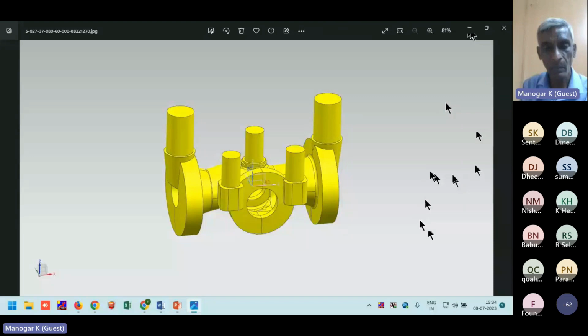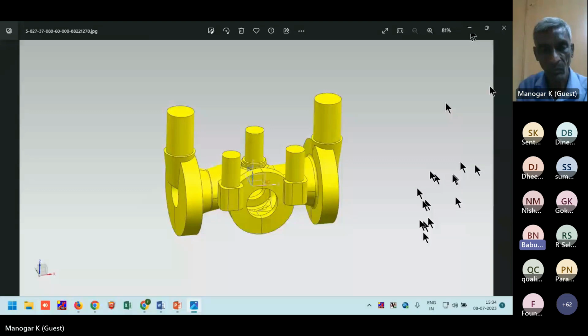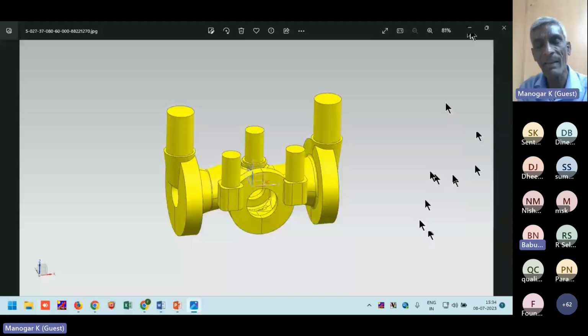Okay. So what is the general feed efficiency for the insulating and exothermic sleeve for the casting? Low alloy steel, you can take it. Less than 6 inch, you can use an exothermic sleeve so that you will have better feed metal. That is a 1.6, that means it gives you 60% efficiency. From a 10 kg riser, you will get 6 kg as feed metal. If it is an insulating riser, then you will get only 4 kg of feed metal. So you are saving 2 kg, no? And the cost also you have to calculate, and economics you have to work out. Anyway, above 6 inch, it is only insulating.